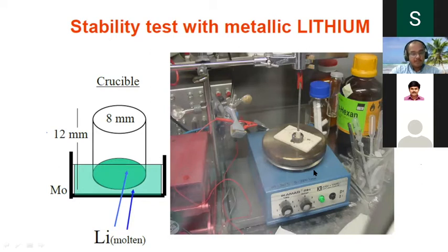But we want to test this; conductivity is 10⁻⁶, leave it. What about the stability? It doesn't have good electrochemical stability against metallic lithium. And what is the fun in doing this research? What we did is just took molybdenum crucibles, put metallic lithium in, heated and melted it, and in that molten state, put the sample directly in as a pellet and see what's happening.